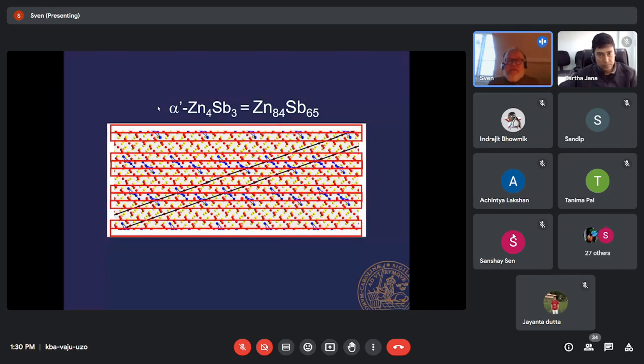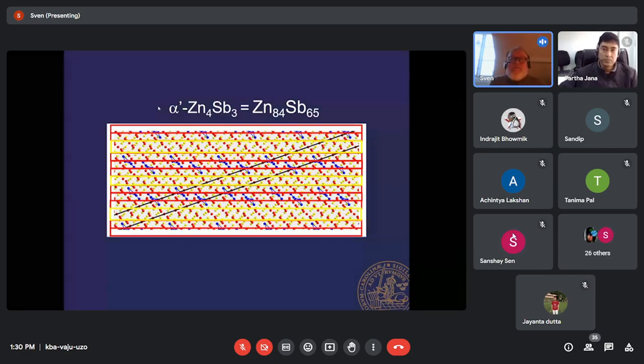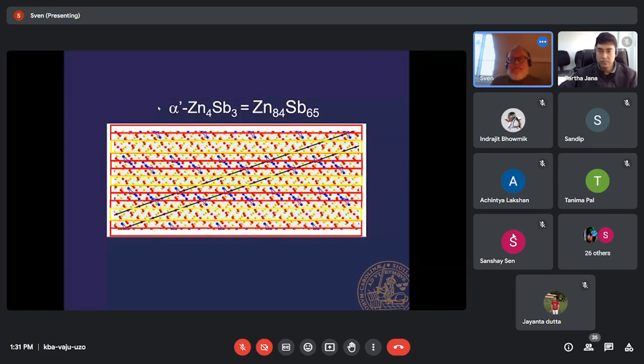Now the slab coming in from the left here is 1.5 unit cells thick. The second is 1 unit cell thick, and the third is 1.5, regarding the structure of the basic cell. So again, we have this strange phenomenon of 2 phases that live very close together and which share interfaces that allow us to intergrow different phases. The amazing thing is that X-ray crystallography allows us to solve structures like this.